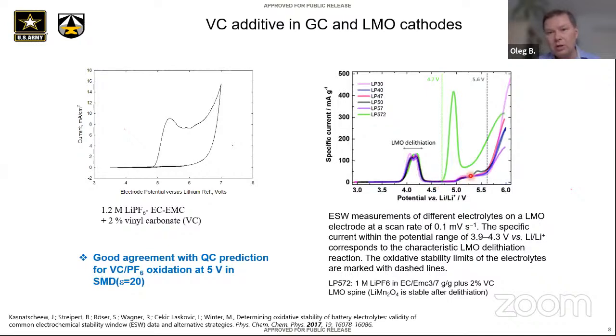They observe that regular electrolytes have a similar behavior as what I showed. So those are LP30 to LP57. Those are EC/DMC LiPF6 electrolytes, but this 572 electrolyte, that's EC/EMC 3 to 7 with 2% of VC, very similar to what we looked at here. And it does have an onset of oxidation potential with a very well-developed peak at about 5 volts. Right? So we do predict 5 volts, we don't predict 4.7, but that's a distribution which you can have distributed. So there could be additional activation rates, which would allow the process to start a little bit earlier.